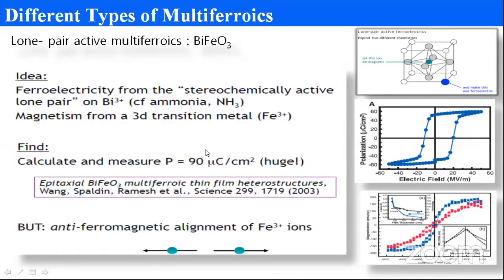Okay. So as I said, bismuth ferrite is one of the well-known materials. So we are going to take one of the components as bismuth ferrite because it has a very huge electric polarization. The problem with the bulk is it is antiferromagnetic. Again, as I said during the introduction, to have a multiferroic material, you need to have a ferromagnetic property. But if you put this bismuth ferrite in a thin film, that shows ferromagnetic property. Okay, so in thin film, because of the lattice strain, you can convert the antiferromagnetic property to the ferromagnetic property. So I'm going to take one component throughout my presentation. Bismuth ferrite will be one of the component materials.